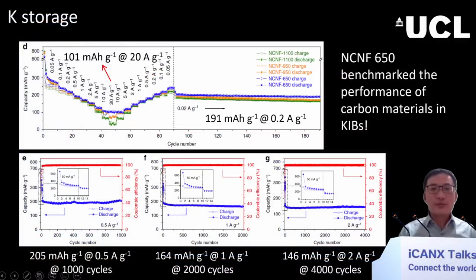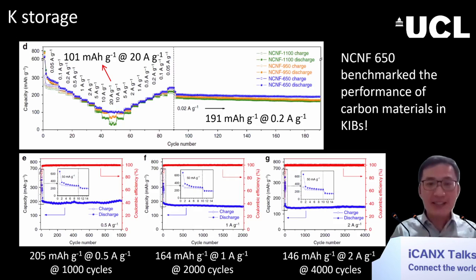which is 50 milliamp per gram, all the way up to a very, very high current density, which is 20 amp per gram. So to put it into perspective, when you charge and discharge a battery under a current density of 20 amp per gram, you are able to fully charge and discharge this battery in a time period of perhaps just 10 seconds or 20 seconds. So that really showcases the ability of this material to be charged and discharged at a very, very fast speed.